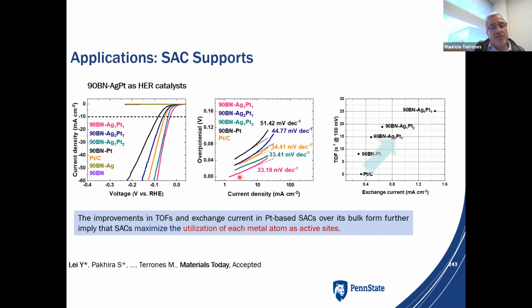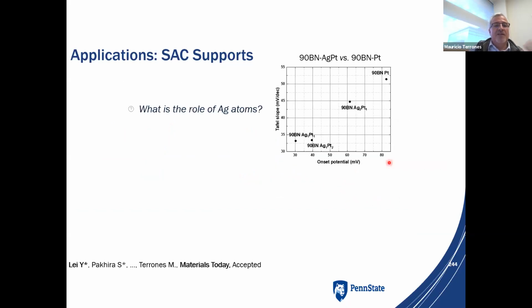And this is the Tafel slope of the boron nitride with platinum. So we can have single atoms. In the case of platinum, we have single atoms of platinum in the lattice. In the case of silver and platinum, we have single atoms on the surface of the silver that is then anchored to the boron nitride, and this seems to be a very good catalyst, right? So we are improving the Tafel slope and the current, and we are making these materials good materials for catalysis.